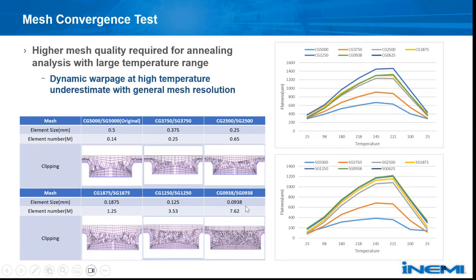So when we compare to the experimental result, both the center gate and the side gate show that the general mesh standards are not good enough for this project validation. Here the light blue curve in the right plot is the dynamic warpage predicted by the standard mesh. The flatness at room temperature is not bad compared to the experiment, but at the high temperature, we highly underestimate the flat warpage value.